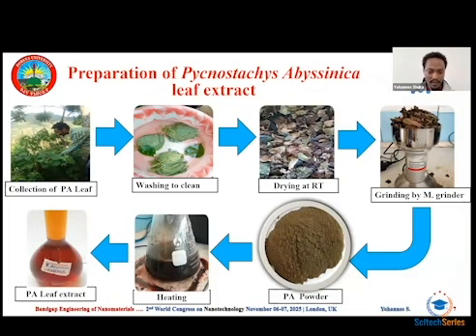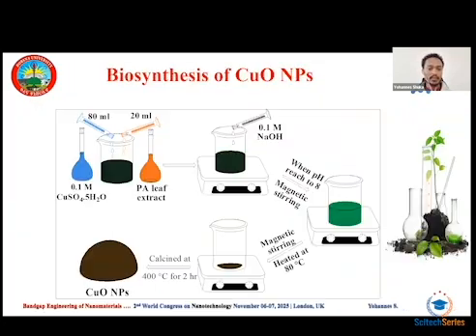This diagram indicates the preparation of the abyssinica leaf extract to be used as a reducing and stabilizing agent for the preparation of nanoparticles. The first step is collection of the plant material from the field, then washing with clean water, followed by distilled water, then drying at room temperature, then grinding by using a mechanical grinder, and then the powder was heated, and finally we filter the extract by using Whatman filter paper.